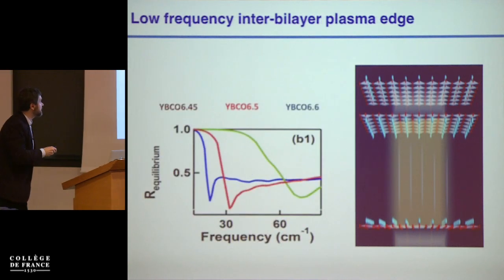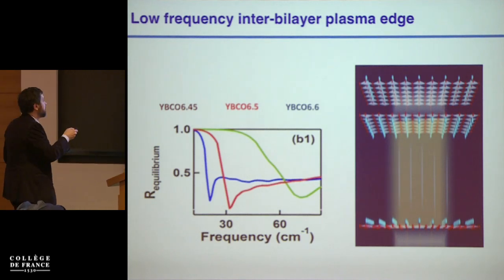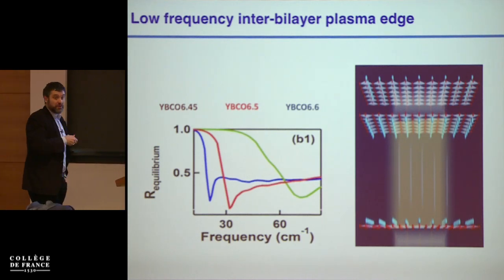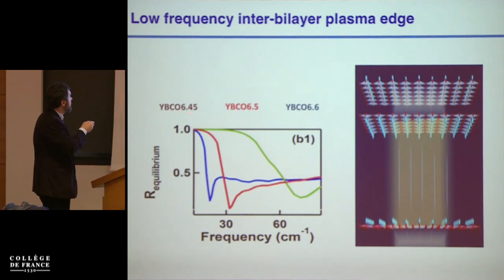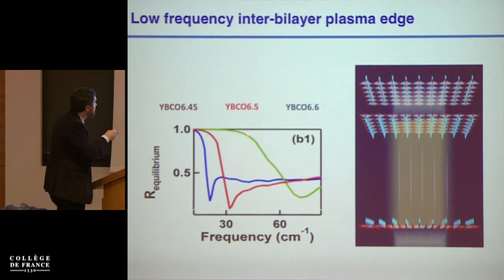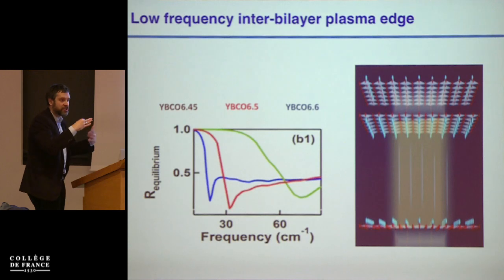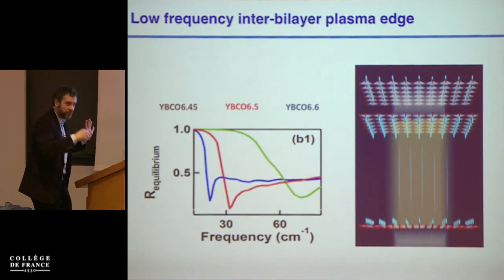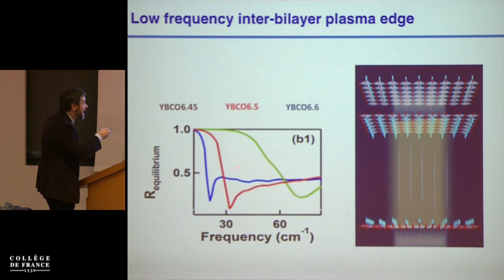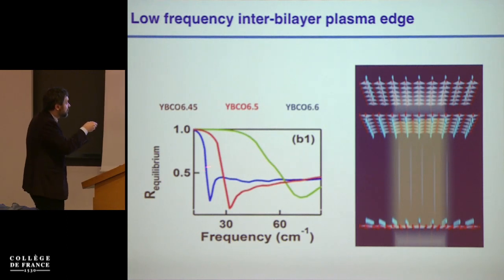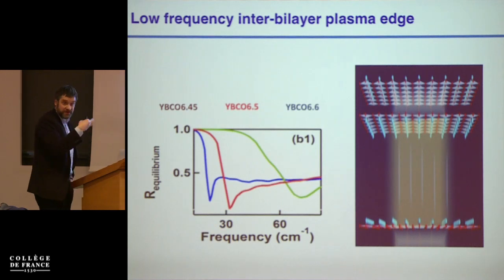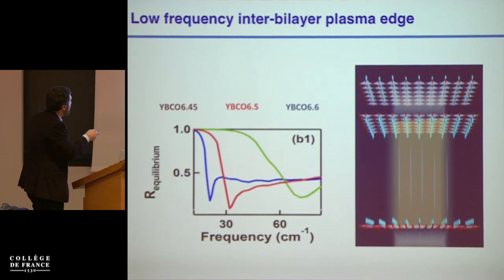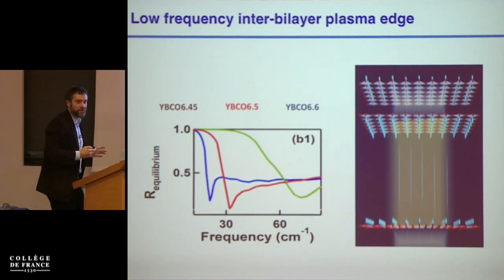Okay, so these are measurements that we do on our samples. These are three edges that you observe at equilibrium below TC in these three compounds. This is the 6.6. You can see this is the 12.5 doped 1/8 compound. This is broad because this is coexisting with a charge density wave. So the tunneling is complicated and it's broader. As you dope it less, the frequency of this tunneling shifts to the red. This is because I have less Cooper pairs, and so the frequency is less, but also becomes sharper because this is better defined. This is widely documented in other papers.